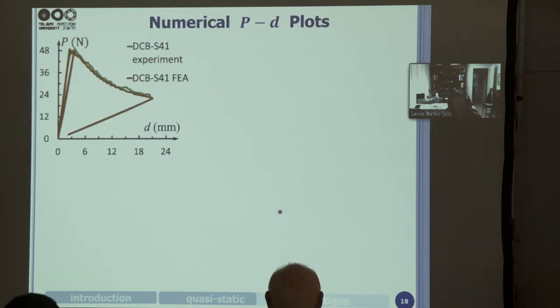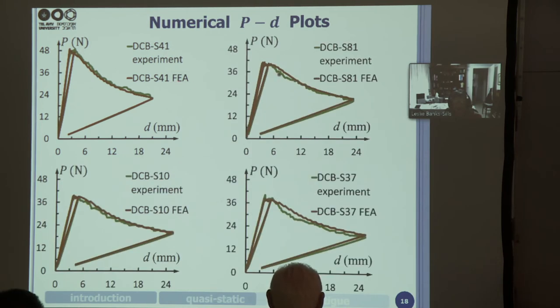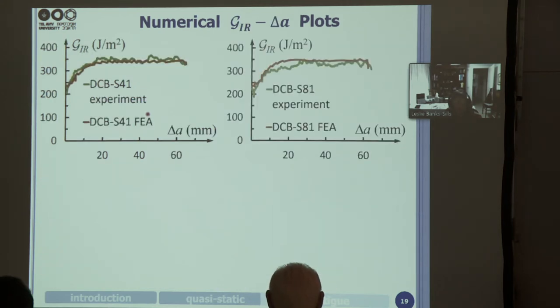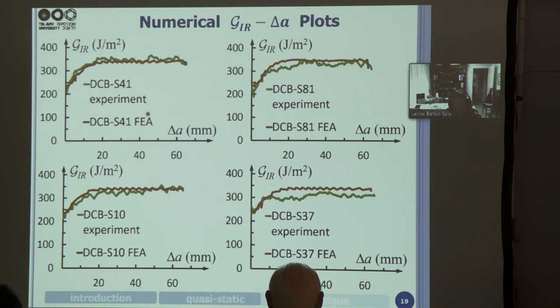And so we obtain numerical values of P versus D. D is the actuated displacement, P is the load. The experimental curve is in green. And you see, using our finite element analysis, we get a very good correlation between the experiment and the finite element analysis. For all of the others, we have a pretty good correlation. It's not as good for specimen DCB 37, but we're very satisfied with it. Our G1R delta A plots, we also numerically simulated them, and we're getting very good results. So this cohesive zone is able to mimic the experiment.